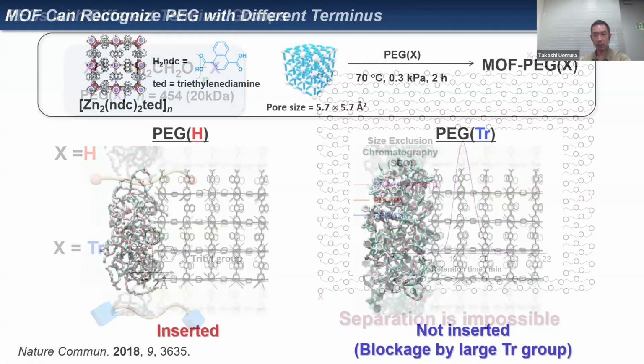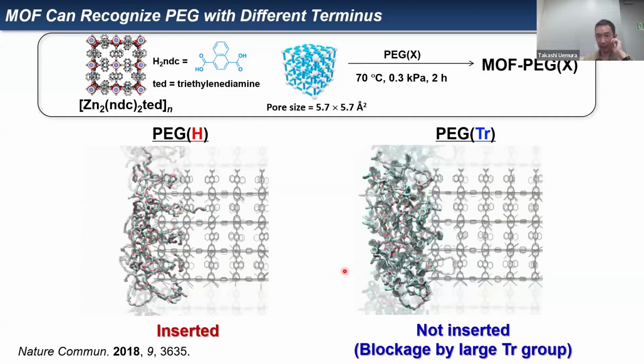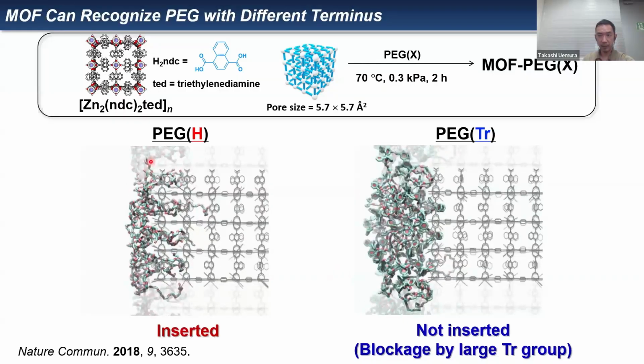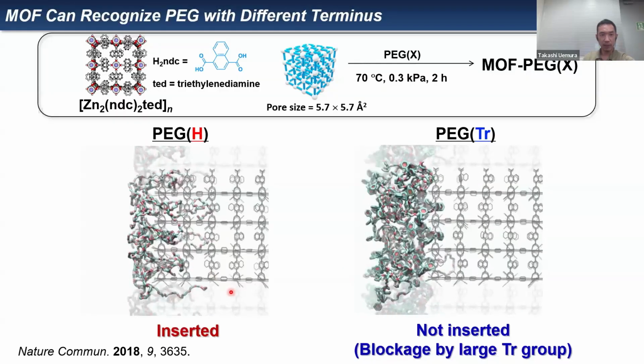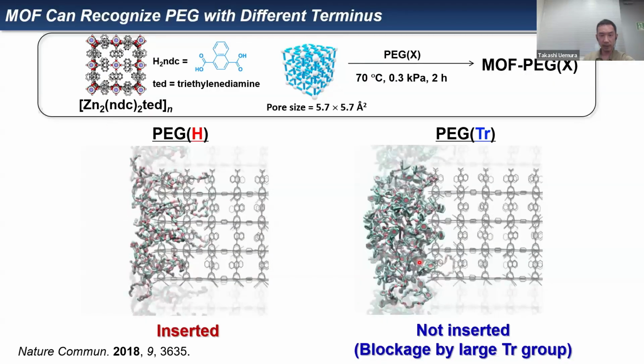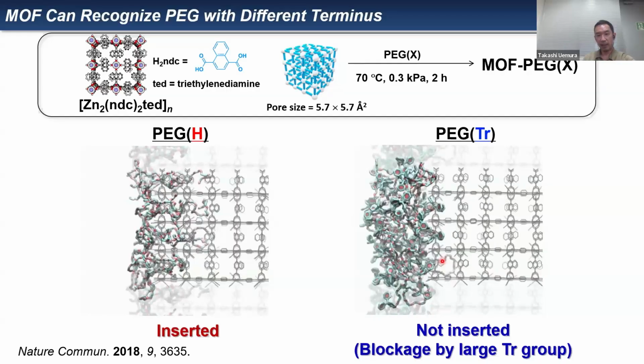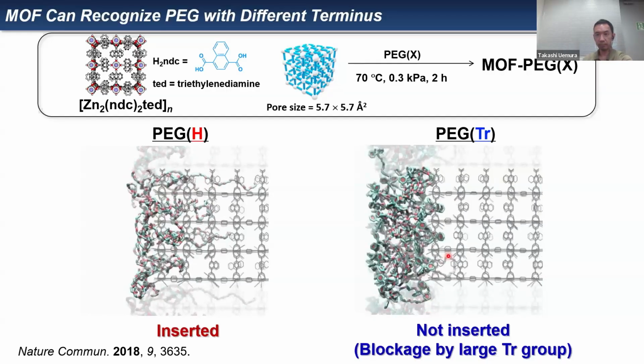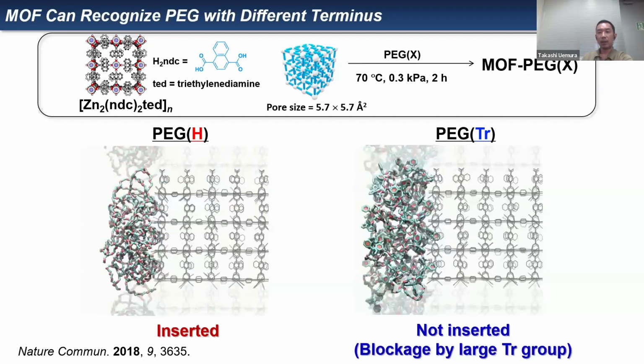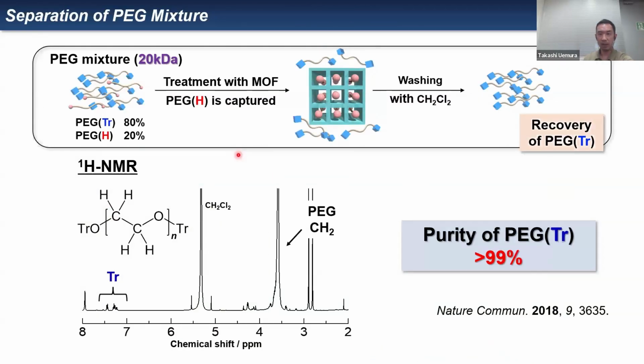But MOFs can do it. MOFs can recognize these two terminal groups. Actually, PEG-H, the unmodified one, can be inserted, but the tosylated PEG is not inserted because of blockage by the large tosyl group, like this. So the actual separation of a PEG mixture is possible. We treated this PEG mixture with MOF powder to capture only the PEG-H inside the pore, and after washing with dichloromethane, we could recover the PEG tosylate with high purity.